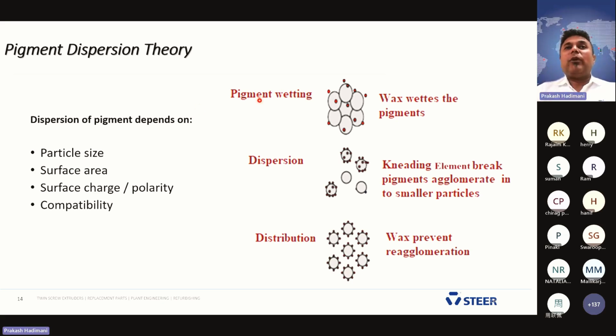What is happening? When the pigments start wetting on each particle side, the bigger one is the pigment, and the waxes start coating on the agglomerated particles. This is the agglomerate particles. When you apply waxes, again, this agglomerate has to be dispersed. It has to be broken down into smaller ones. We are using kneading blocks, again applying more energy to break these bonds. Breaking the agglomerates into smaller particles, we call this phenomenon dispersion.